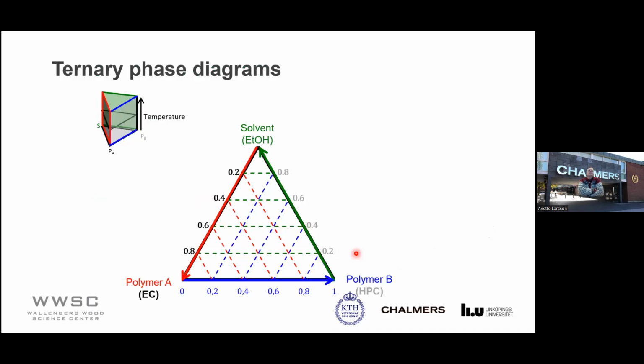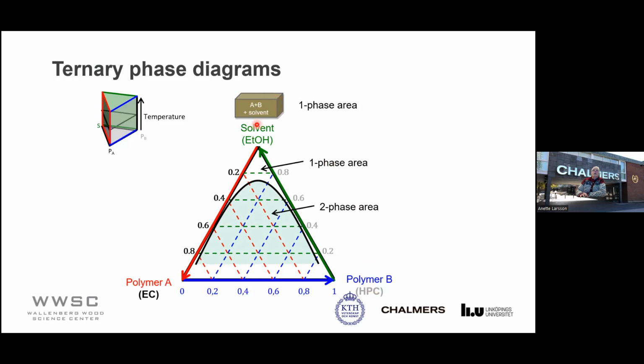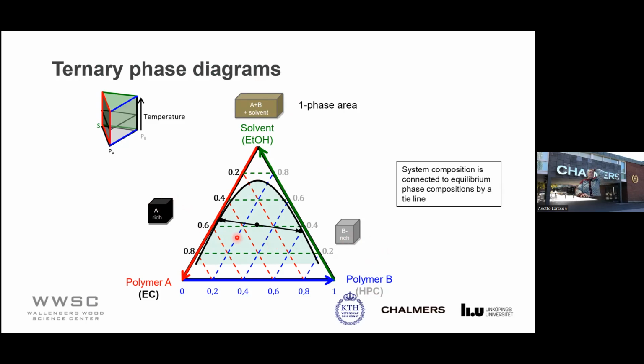And so we have a phase diagram here. So we have the ethanol up here. We have the polymer A, the ethyl cellulose, and we have the B, the HPC. And we start with a one-phase area, and we have a two-phase area here. So if we start in this one-phase area up here, and we take away the ethanol, we will end up in this two-phase region, and we will get a phase separation with an A-rich phase and a B-rich phase. And then they are kept together here with a tie line.